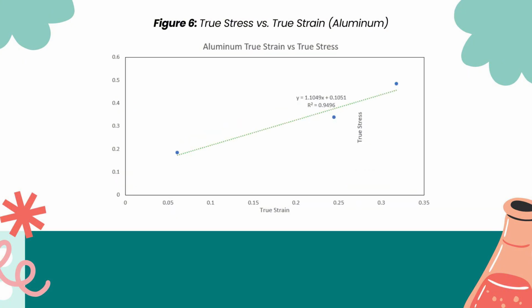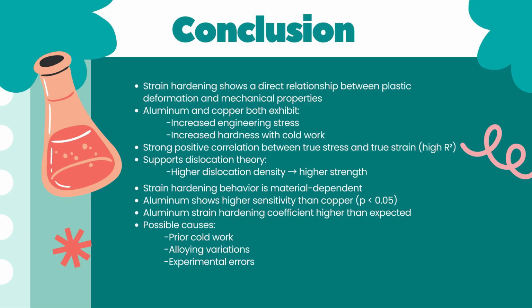In this slide, we're looking at the true stress-strain relationship for aluminum. You'll notice the trendline equation y equals 1.1049x plus 0.1051. That slope tells us exactly how much the material hardens as we deform it. With an R² of nearly 0.95, our data shows a very consistent strain hardening effect. Essentially, as we stretch the aluminum, we are making it harder to stretch further because of dislocation pile-ups within the material's grain structure. Strain hardening shows a direct relationship between plastic deformation and mechanical properties.